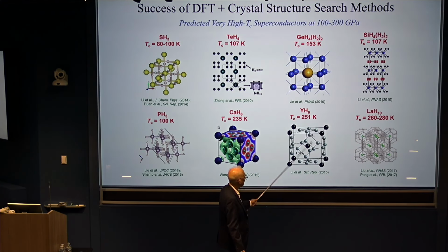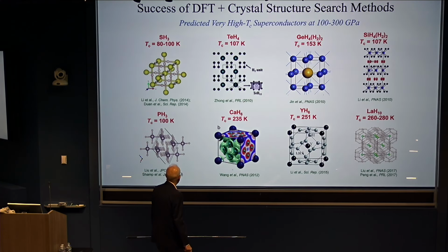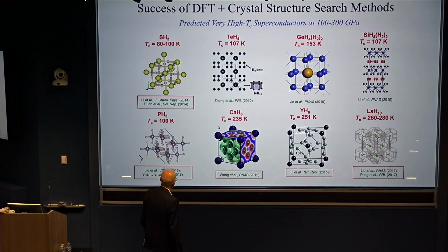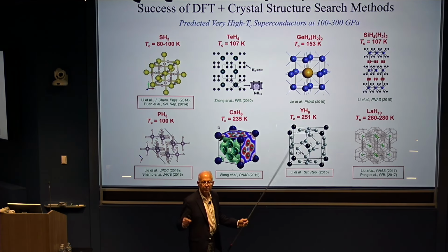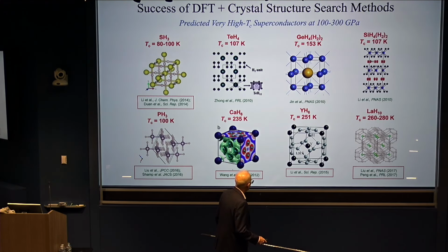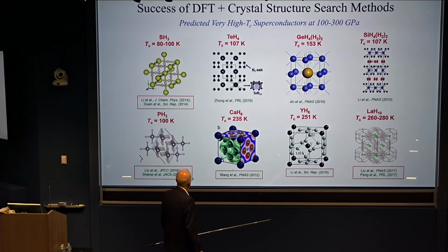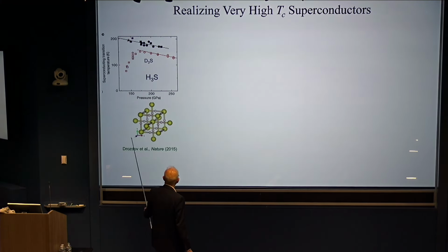So these are really intriguing structures from the standpoint of hydrogen, very hydrogen-rich. And in fact, the ones here in red were, over the years, discovered and confirmed. And basically, the structures were confirmed, and pretty much the TCs using the conventional theory of superconductivity. I just want to give you an example of the two first ones, and that is the case of H3S,